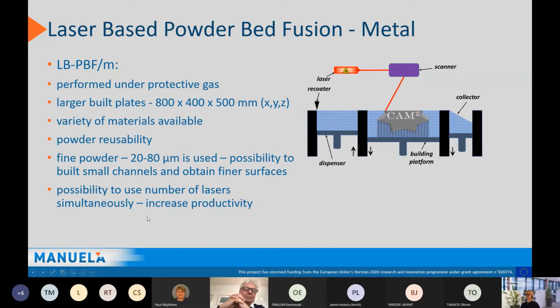Modern techniques today can use a number of lasers in parallel, say up to 4 or more lasers. That increases productivity. But we can also boost productivity by working with greater layer thicknesses, as we do inside Manuela, which increases productivity by 3 or 4 times compared to the standard processing parameter settings. Next slide.